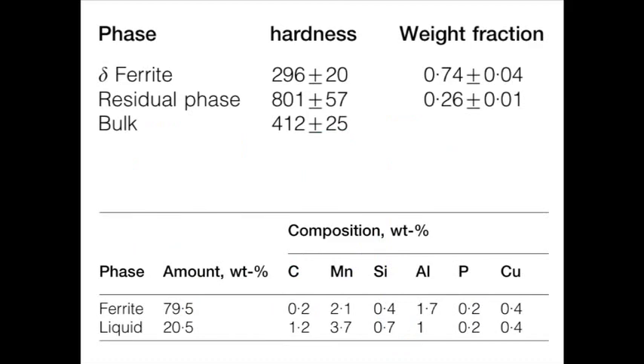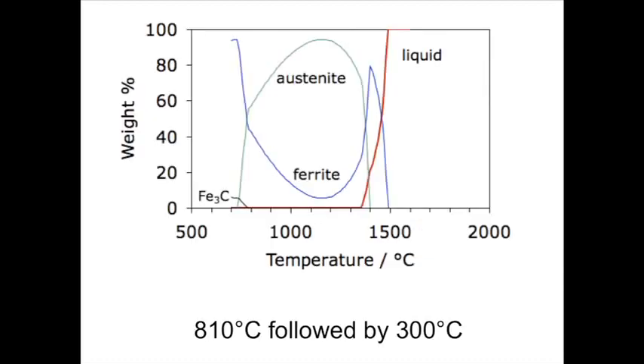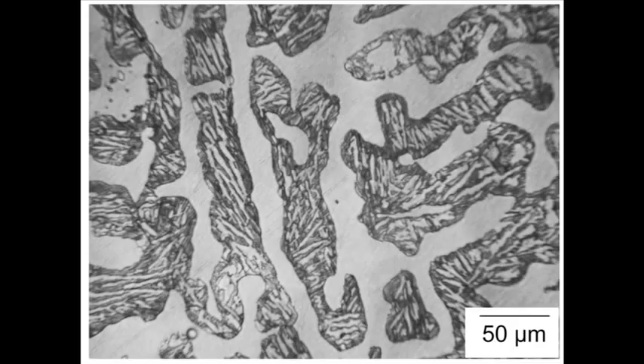This is the constitution. So there's about 80% total of ferrite. And then we end up with the remaining liquid solidifying into austenite. And this is now the recalculated phase diagram for the actual alloy that we made. And we then heat treated this alloy to produce bainite in the regions which are austenite. So it looks slightly different here. Okay. So this is the very first alloy.